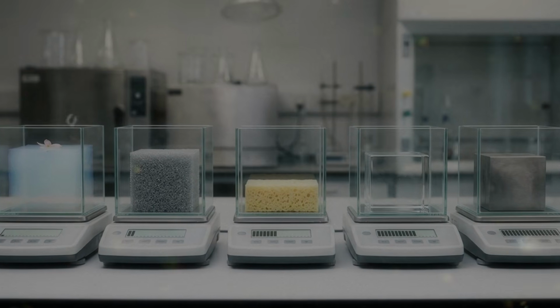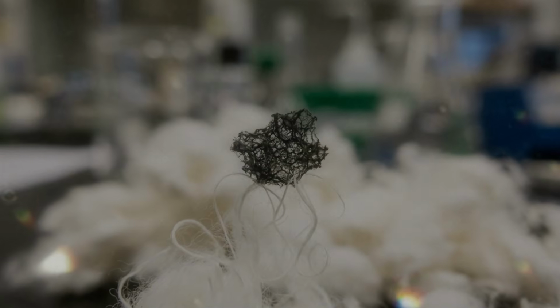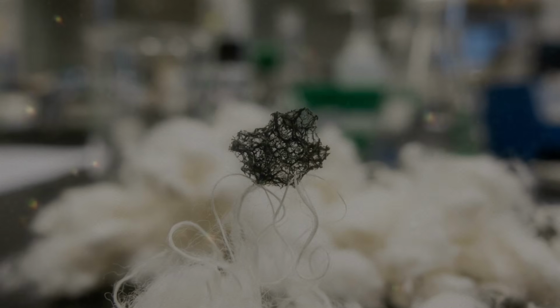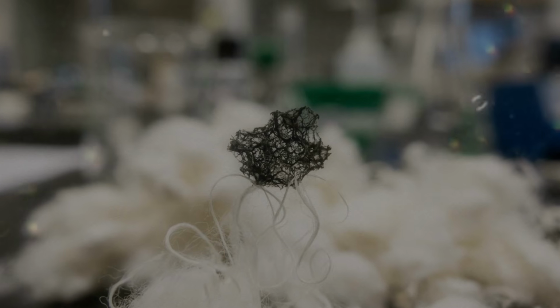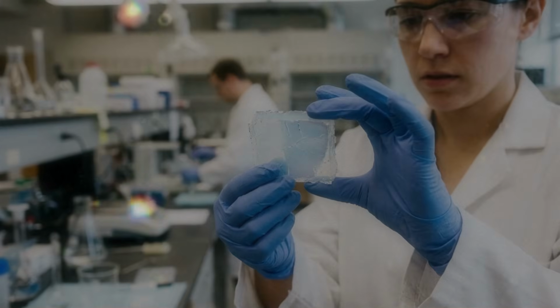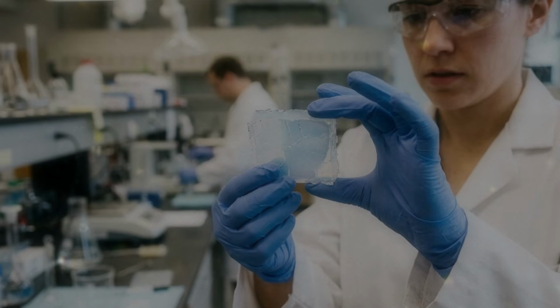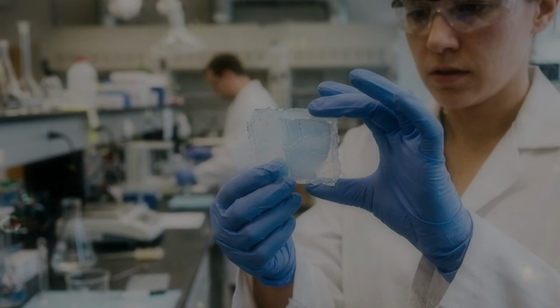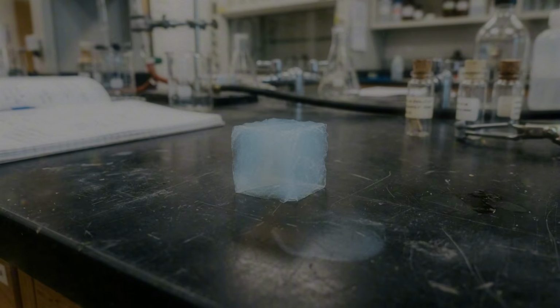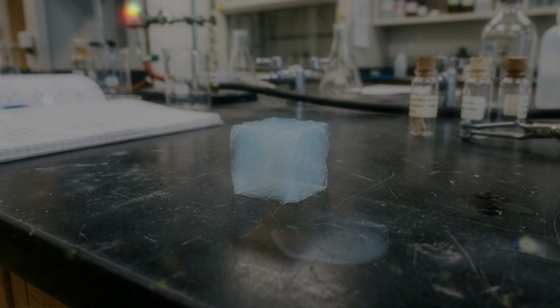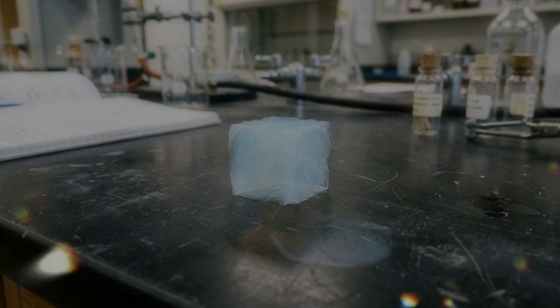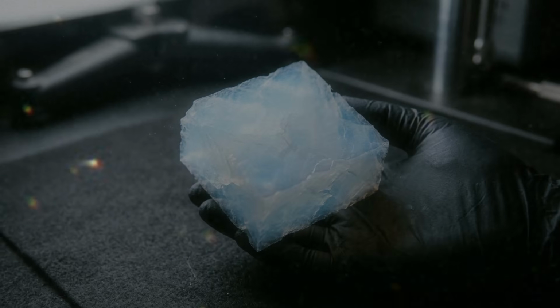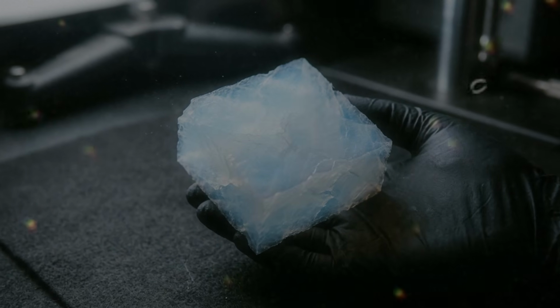The surface of the aerogel can also influence sound. A sealed surface prevents air from entering the pores, reducing absorption. An open surface allows better interaction, but may release dust or absorb moisture. Protective coverings must therefore be chosen carefully. A fabric can hold the material together while allowing sound and air to pass. A solid film may improve durability but reduce acoustic performance.